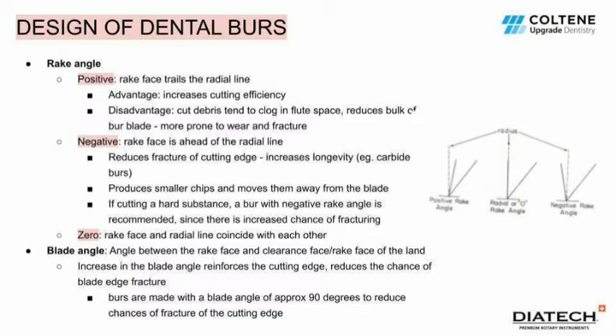In burrs with a negative rake angle, the rake face is ahead of the radial line. This reduces the fracture of the cutting edge and increases the longevity of the burr. An example of this is carbide burrs. Negative rake angles produce smaller chips and move them away from the blade. And if one is cutting a hard substance, a burr with a negative rake angle is recommended because there is an increased chance of fracturing. And since the bulk of the blade is not reduced too much, it reduces its tendency to fracture.